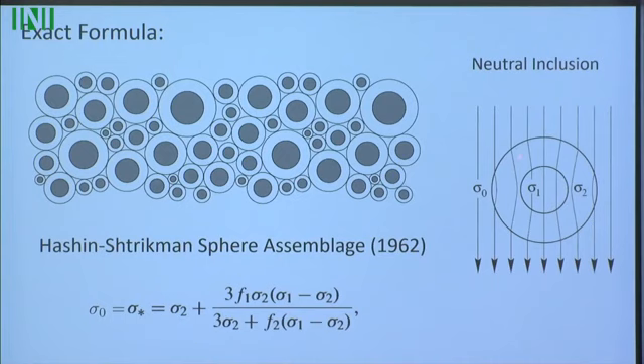And if you've got one inclusion like that that's invisible to a uniform field, you can add another one and so on, fill up all space with these coated inclusions. And at each stage, the average properties are determined by sigma naught, and that doesn't change. And that appropriate value of sigma naught, which gives you the neutral inclusions, is given by this formula. That's a straightforward calculation.